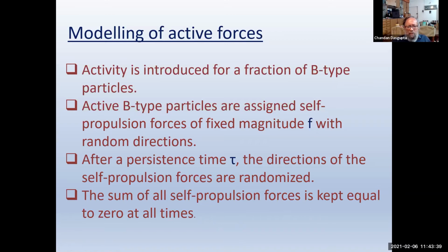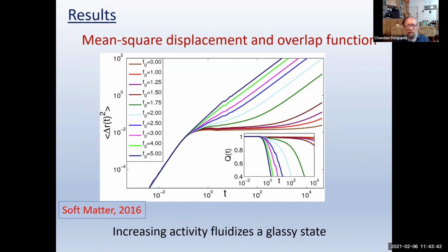Many things can be measured, but I'll show you some data which shows the specific behavior that we are interested in. Again, this is the mean square displacement versus time, which tells us about whether the particles are diffusing or not. And this F0 is the strength of the active force. F0 equals 0 is basically the passive limit. So in the passive limit, this is the lowest curve. You can see that the mean square displacement increases initially, but then it levels off, and this is the caging that is mentioned in the context of the glass transition. So the system was basically a glass at this temperature in the passive limit.